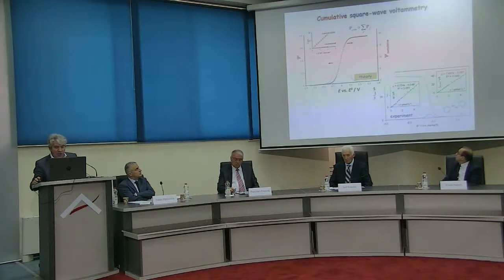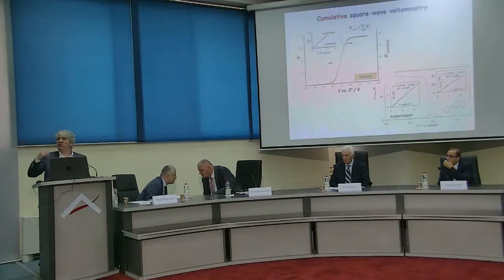Sometimes I have a really clean response, a clean peak, reflecting only the electron transfer. And if I go really into very low concentrations, when the signal is sometimes even not measurable, then with such a good technique, having information mainly due to real electron transfer, I have the right to process the data. For instance, by a simple, very primitive integration process, I can transform this peak into a sigmoid curve. But the intensity of this sigmoid curve is actually almost two orders of magnitude higher than the intensity of this peak here, which of course has meaning with respect to the analysis, detection of low concentrations, and so on.